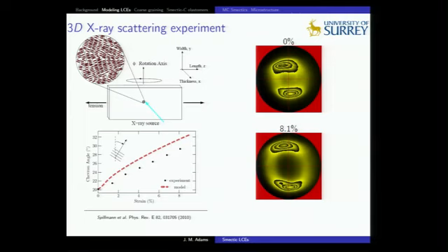So we're looking down on these small angle X-ray scattering patterns here, and as you stretch them, you can see that they start to spread out in a circle here. These are the layer normals spreading out on the surface of a sphere, so they're stretching in various different directions, both in the plane of the scattering plane that we saw earlier and perpendicular to that. So this is strong evidence that is consistent with the layer normal deforming as the cofactor.